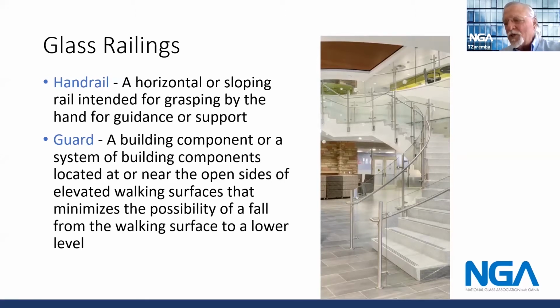However, in the situation where you have baluster glass, either panels or other types of glass balusters, the code requires that there be a top rail or a handrail at the top of the balusters that attaches to at least 3 balusters. Now, there's only one exception to that rule, and that is if the baluster is laminated and has been tested to remain in place after impact or breakage pursuant to ASTM 2353. So top rails are required in glass balusters. They are not required in infill panel guards.